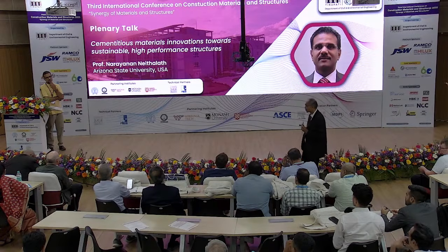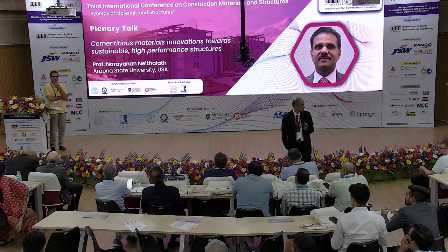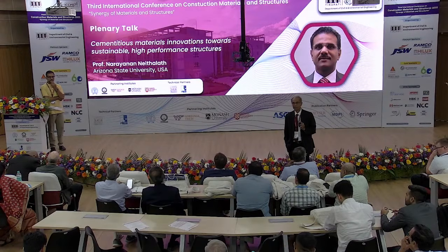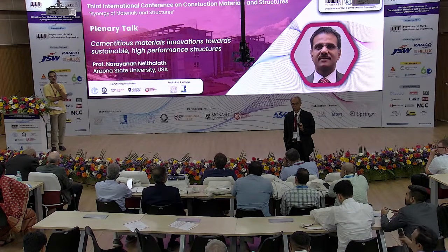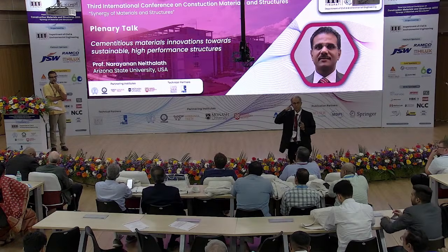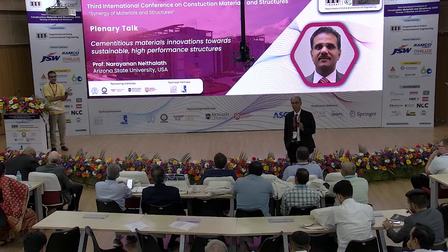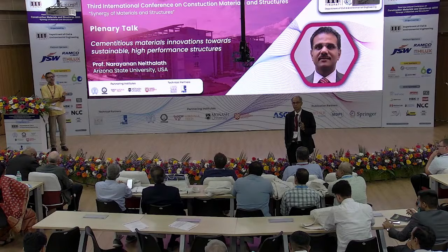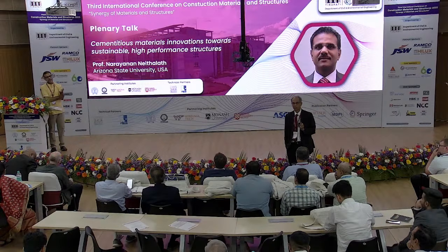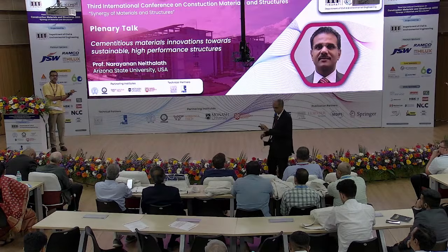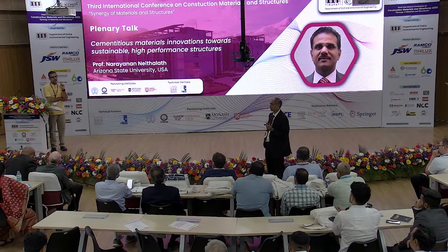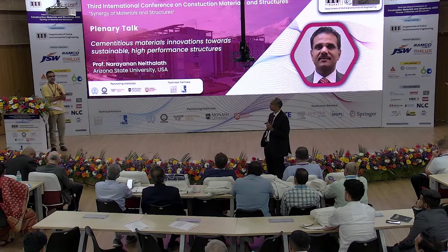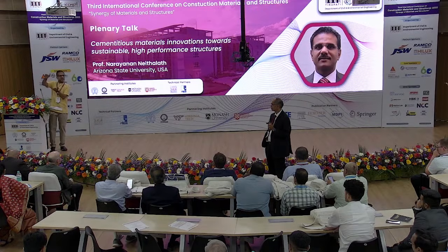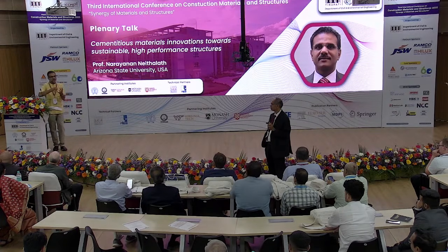Whether there is the possibility, if we are talking about really saving the carbon credits. So if you increase the reactivity of cement, if you increase the blend fineness from 350 meter square per kilogram to 500 meter square per kilogram, which I think many of the cement companies are already getting there in India, and you reduce the cement content by 200 kilograms per meter cube, you have a valid point. But are we reducing the cement content when we increase the blend's fineness? Because we increase the blend's fineness to further increase the strength. That's the idea, right?